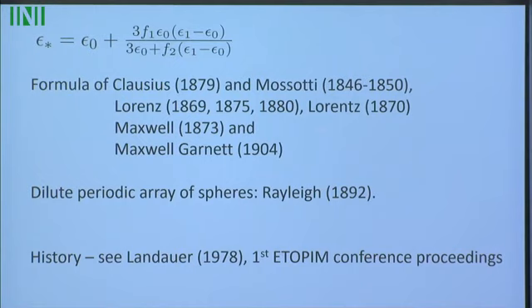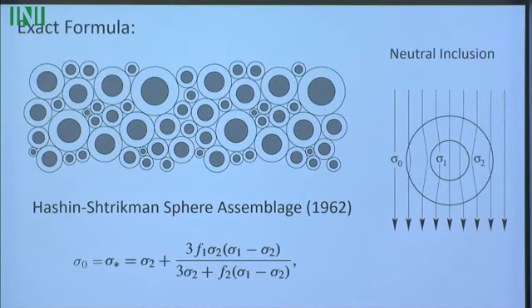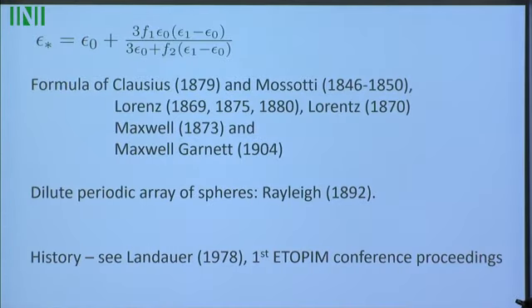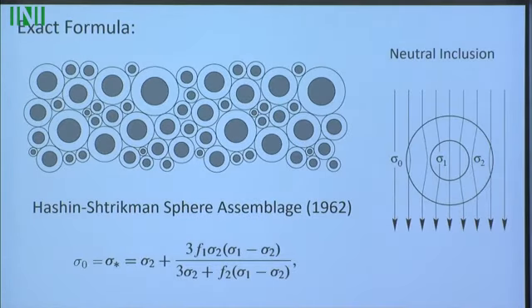So there was a lot of debate about these different approximations. It was settled a little bit by Rayleigh, who noticed that it becomes exact in the dilute limit of a periodic array of spheres. And there's a nice historical article here if you're interested. Later it was realized that this is actually an exact formula. Here it's for conductivity, but it's exactly the same for the dielectric constant. Compare that formula up the top with this formula here.